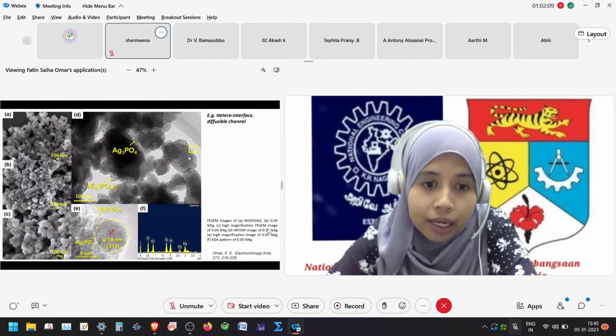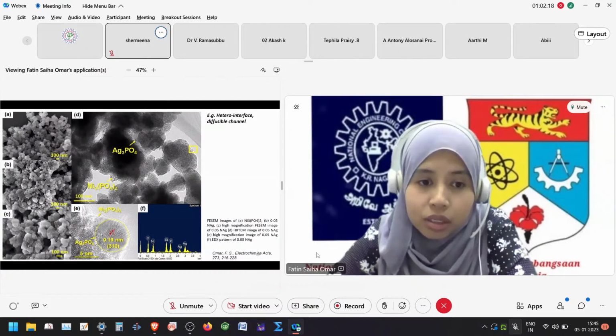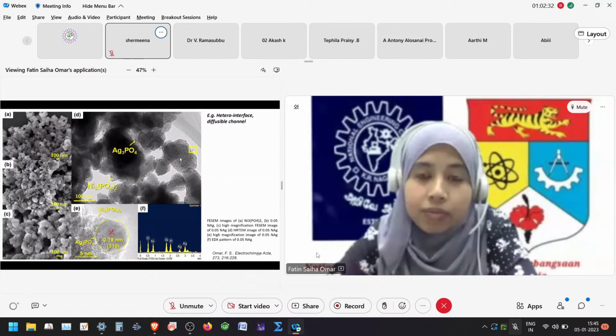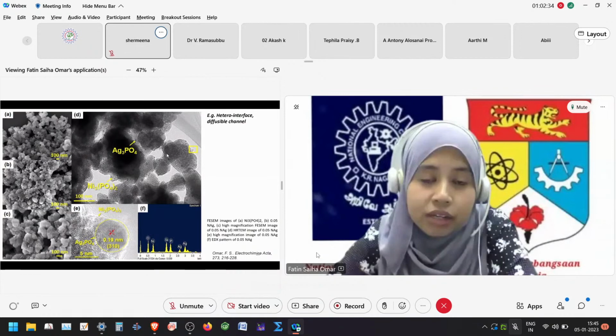And this is the close-up view. Silver phosphate has lattice fringe, so it means that silver phosphate has crystalline structure, while nickel phosphate doesn't have any lattice fringe, so it means that nickel phosphate has amorphous structure. Like I said previously, if the material has a lot of pores, it means that they can provide more channels for the diffusion of electrolyte ions.